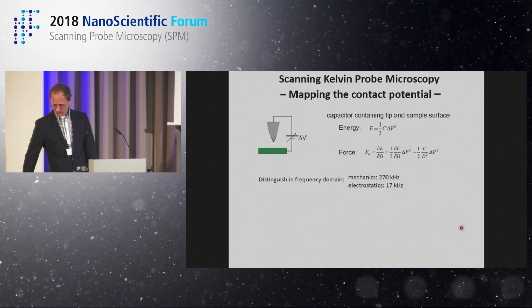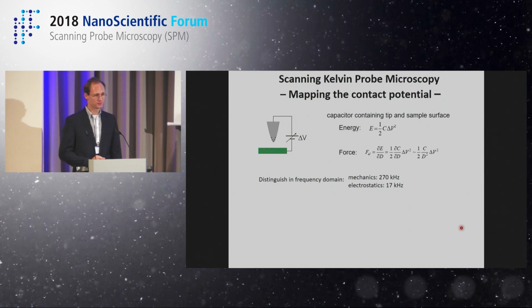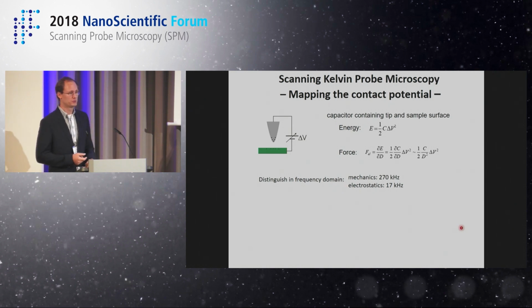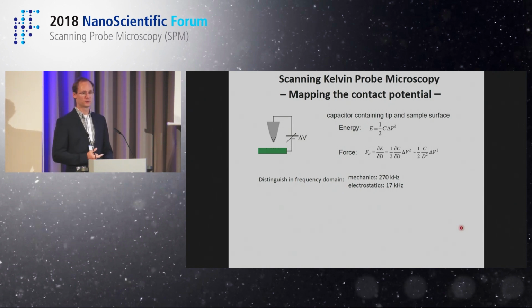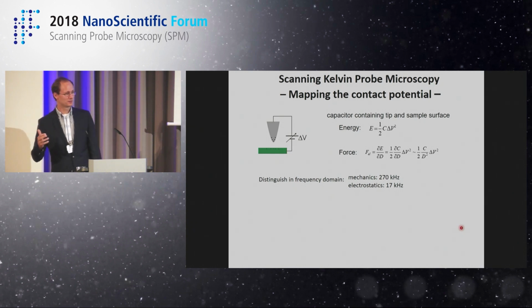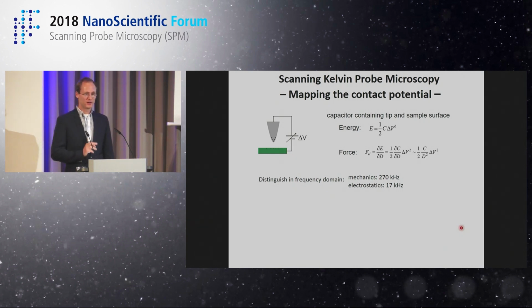Of course, then it's not so easy anymore to measure forces, because at the scales when we are almost in contact with the surface, we do not have only electrostatic forces, but we have van der Waals forces, we have a lot of different forces. And that's a problem when you do the electrostatic AFM experiment always. So you have to find a way to separate precisely the electrostatic forces. Now, the nice thing is that thinking of frequency space and dynamic AFM, there is a very, very elegant way to do so.